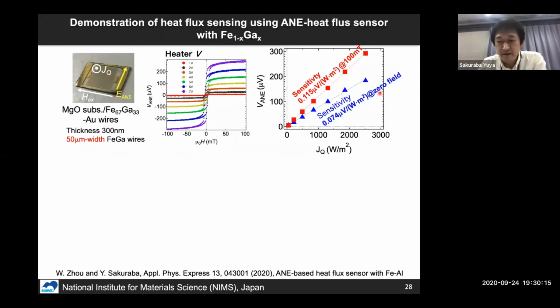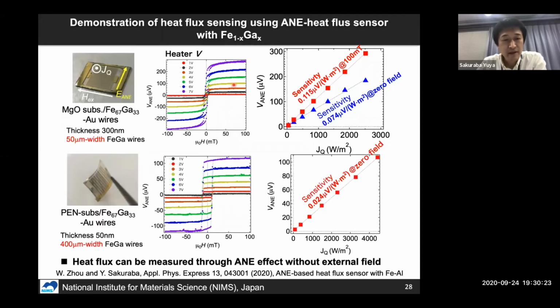And this is the result on the solid MgO substrate, a device grown on the solid MgO substrate. But because iron gallium can be grown on a very flexible sheet, we also fabricated a prototype of a heat flux sensor on a PEN substrate sheet. So this is a very flexible sheet, and we patterned the iron gallium wire on this sheet.